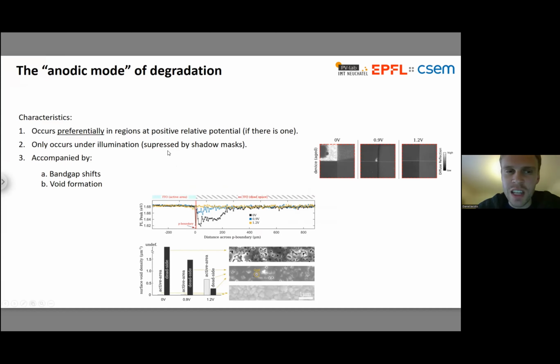As far as I can tell, it only occurs under illumination. When I've tested devices just at elevated temperature in the glove box with no light, I don't see any of these phenomena occurring. And microscopically, we did a bit to characterize this degradation mode, looking at devices in PL and in SEM. I'm not going to go too much into detail now, but I'm happy to answer questions.